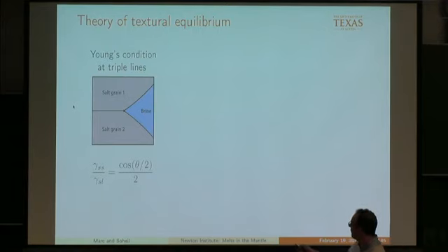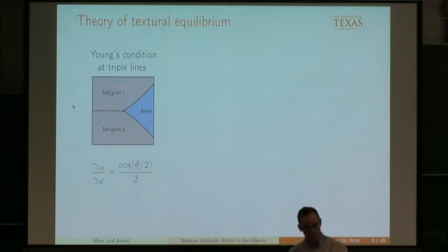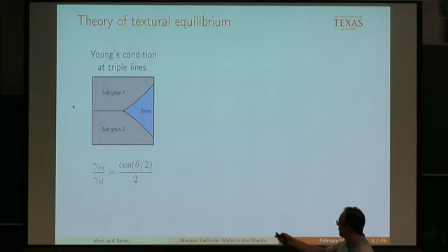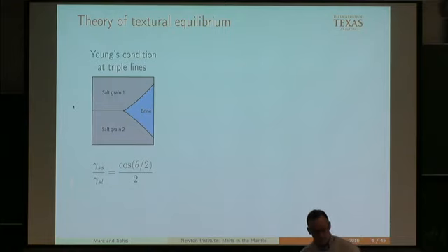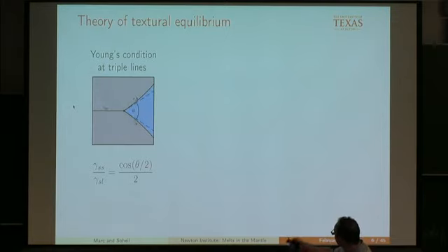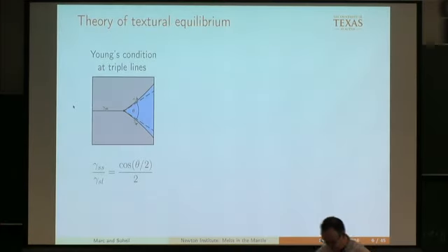As I said, we're funded by an oil company. So the basic idea is if you have two salt grains, and we're on the pore scale, right? It's not a planetesimal, we're on the pore scale. So here's a salt grain, here's another salt grain or an olivine grain. Here's a brine or a melt, and here at this triple point they come together. Mechanical equilibrium simply requires that the ratio of the surface energies is related to this angle theta, which is the angle in the fluid here.